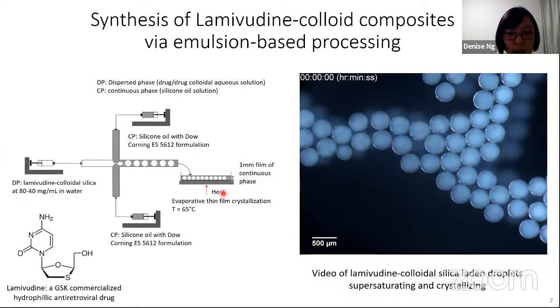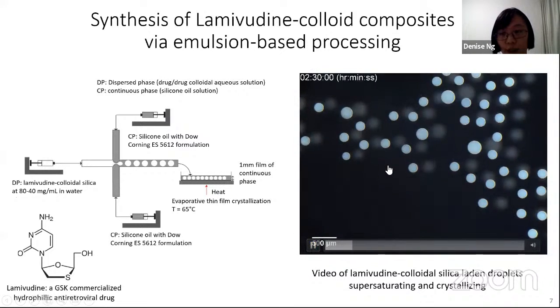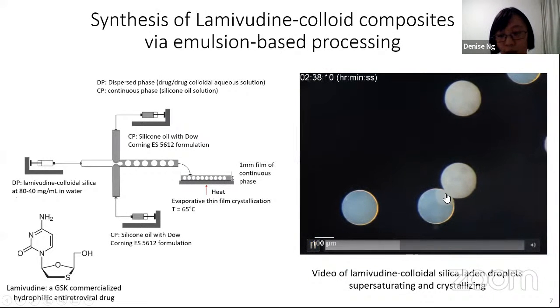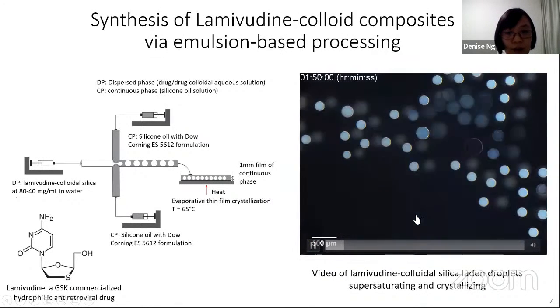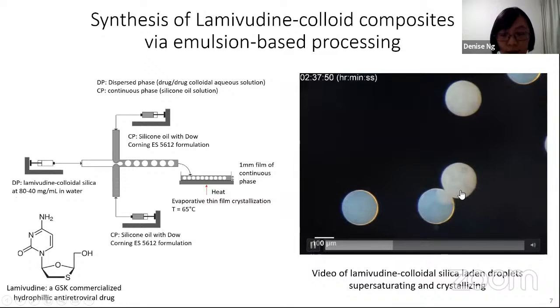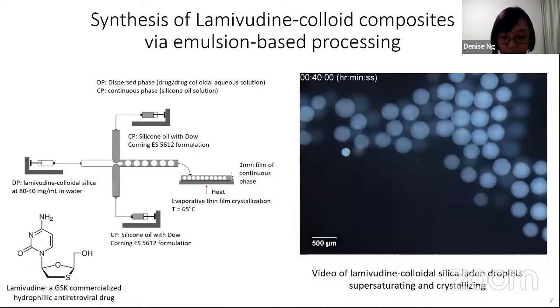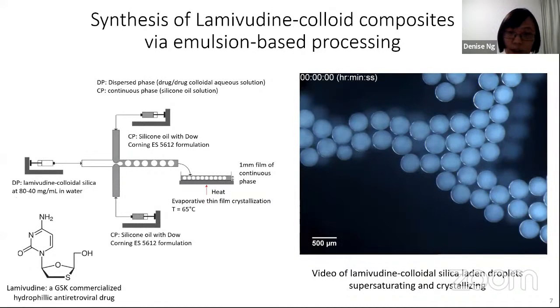in this case the silicone oil. Then we apply heat at 65 degrees to evaporate the water, and this results in the droplets undergoing shrinkage. After that, crystallization propagates from one droplet periphery across the entire droplet. At the end of the process, we wash our particles to remove any traces of the surfactant. Then we dry them under vacuum and subject them to further characterization.